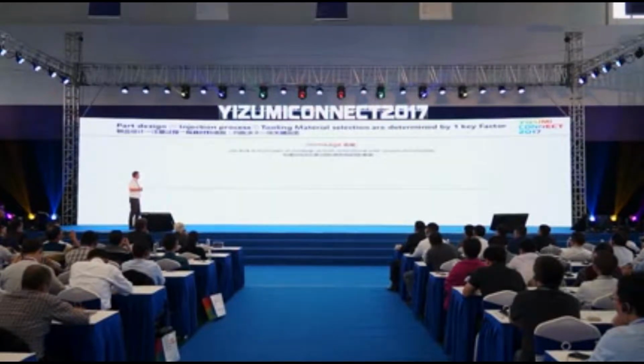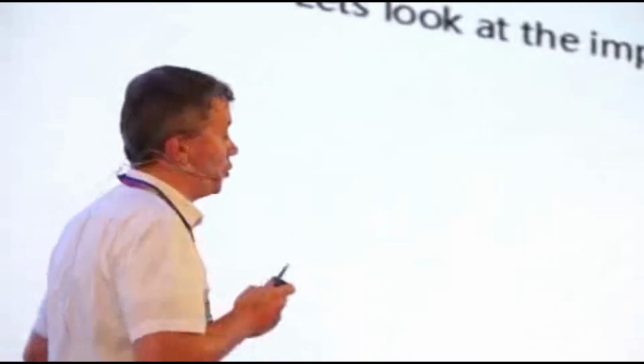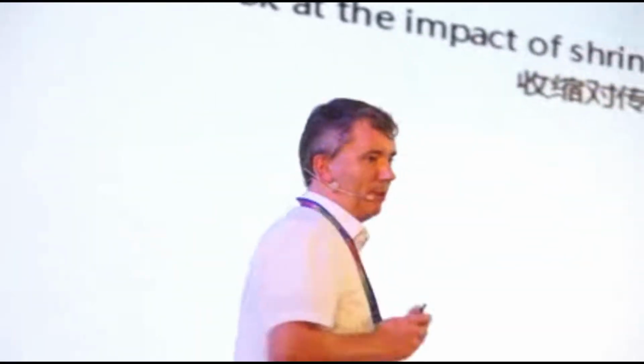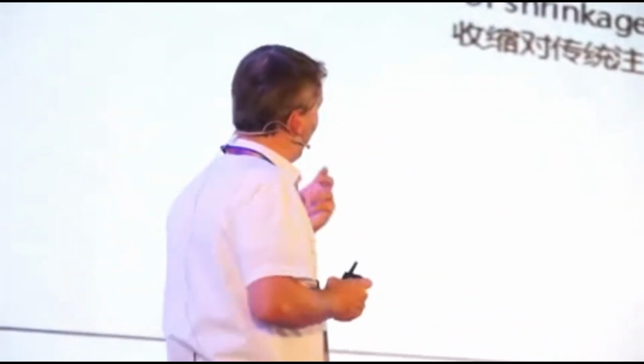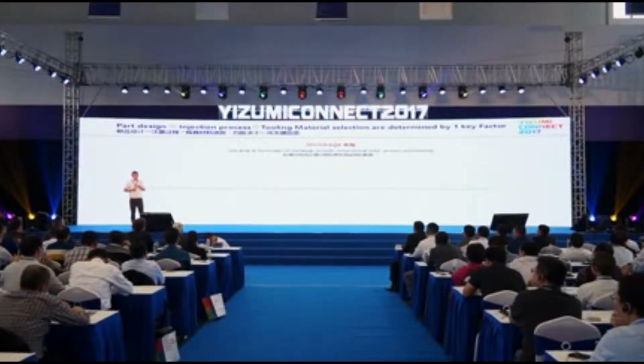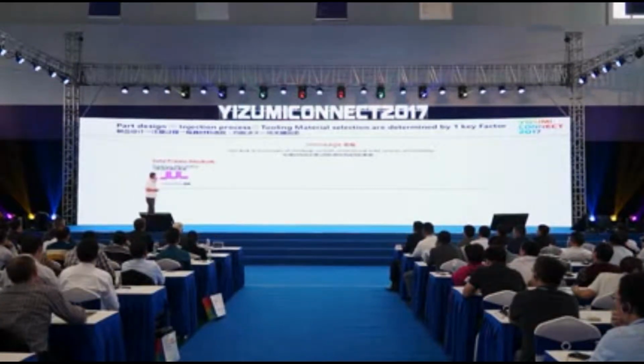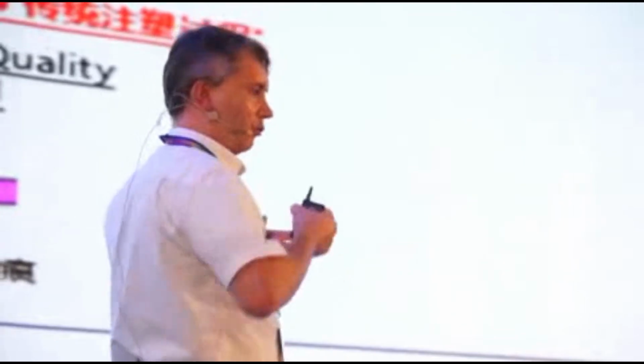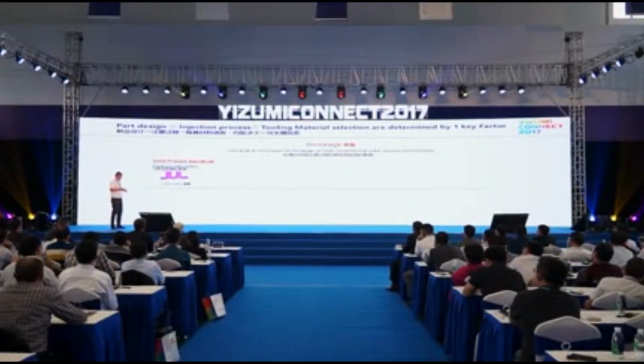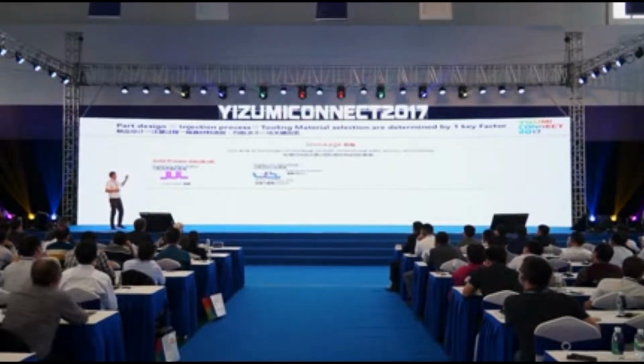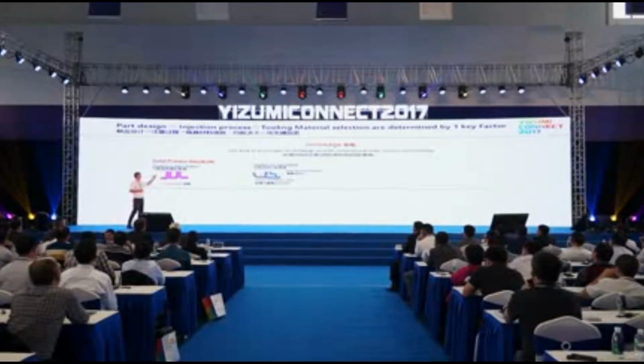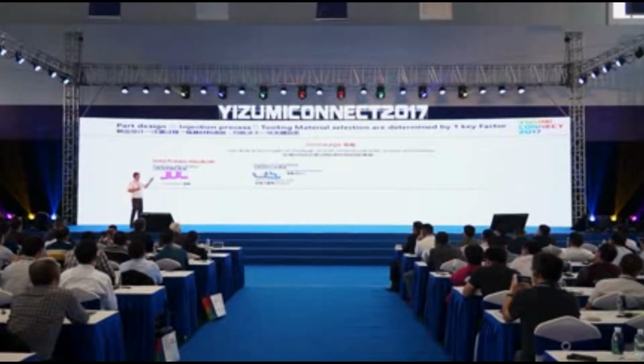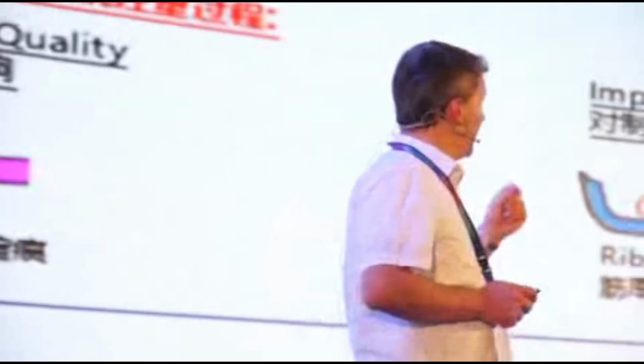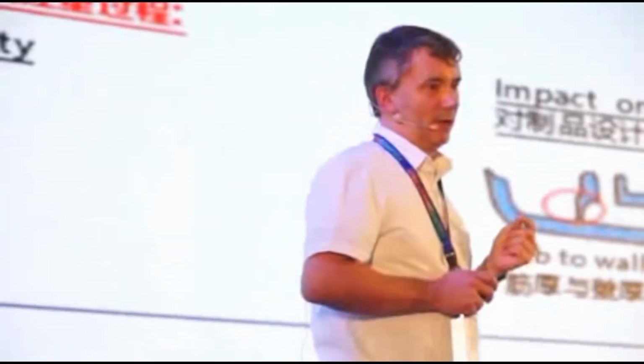So part design, injection process, tooling material are determined by one key factor. This is shrinkage. Everything we do in plastic is driven by shrinkage. So let's take a look at the impact that shrinkage has on both conventional and foaming process. So you see here, a common problem we have is sink marks. So because of the shrinkage and the flow lengths, we have an issue with the quality for visible parts. So the effect on the part design is that we need a rib-to-wall ratio of maybe 30%. We have to have special tools to demold and the doghouse design. The impact on the injection process is we have high pressure and we have a longer cycle time.